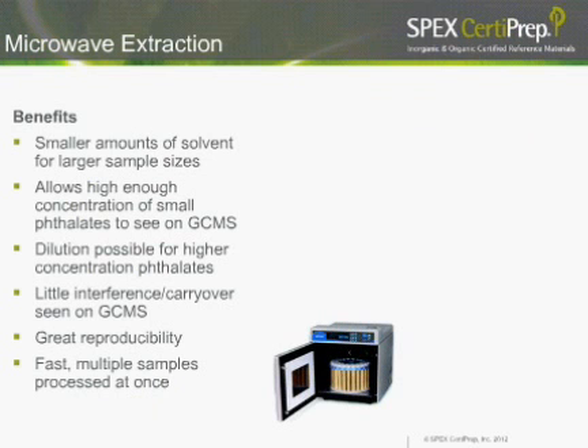What we found was a benefit of the microwave. We were able to use smaller amounts of solution, higher amounts of sample, and get a very efficient extraction out of it. We were able to see the very small phthalates and things like Bisphenol A without any problem. We were able to see them in scan mode, as I said. And when we found that some of the phthalates were out of our analytical range, they were just too high, we were able to safely dilute those samples down and retest them to get them into our analytical range. One of the best parts is we saw very little carryover on the GCMS, so it gave us great reproducibility.